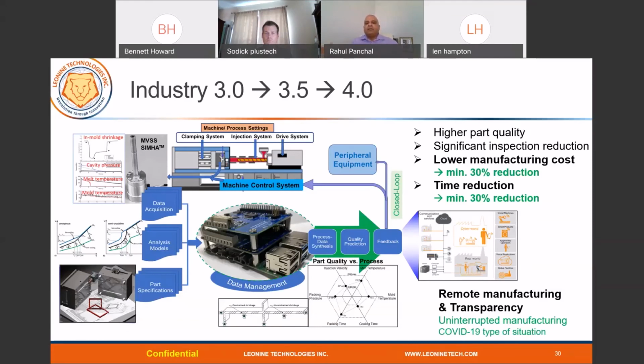Ultimately, you may have a longer part, but the melt flow is controlled by the thickness of your cavity. If you have one section that is 3 millimeter and another that is 1 millimeter, that can be a different story, because that's a drastic change in the thickness. But when measuring the shrinkage at the thickness, we don't have to worry much about the transverse or biaxial, the linear X or Y direction shrinkage.